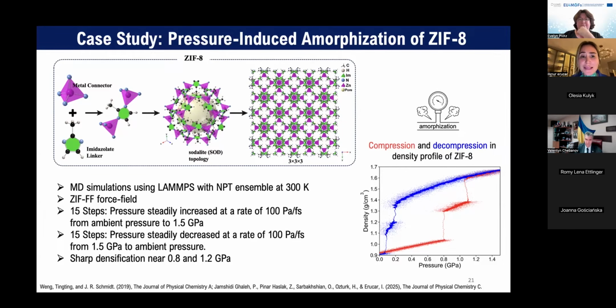Of course, we need a force field to compute the interactions. Here we use ZIF-FF. This force field was developed by Schmidt's group. What we did here is perform 15 steps. Let's say you increase the pressure and then you can go back using these 15 steps. Here you can see the sharp densification can occur at 0.8 gigapascal or 1.2 gigapascal. It can be a metastable phase. What is strange here is the blue curve. It's like a sponge-like material, right? So you can go back, even when you perform a simulation. It's so interesting in my opinion.